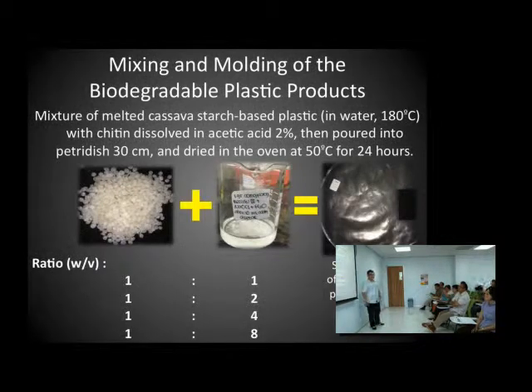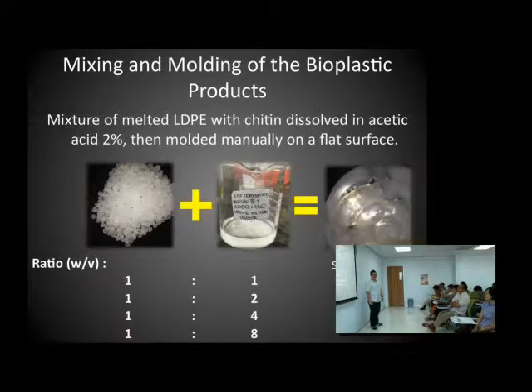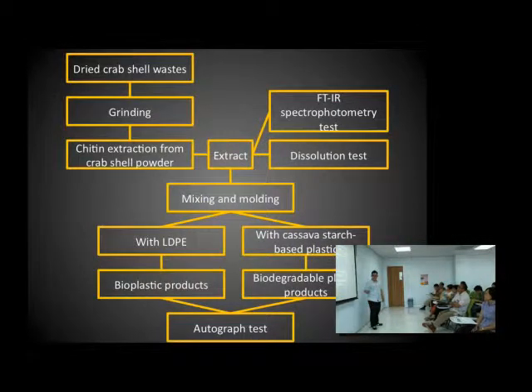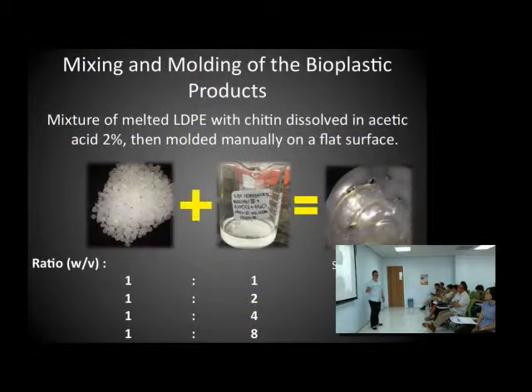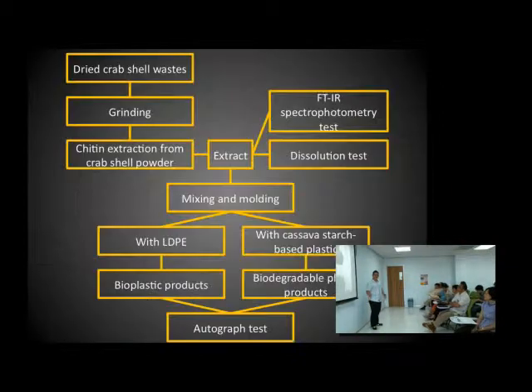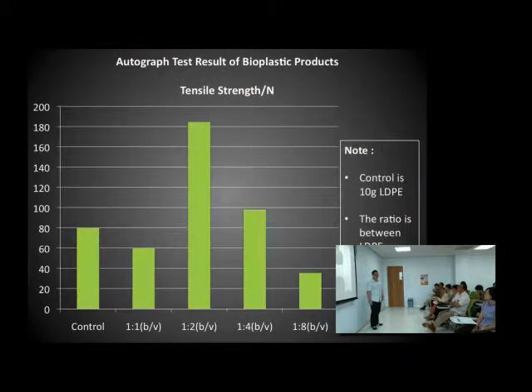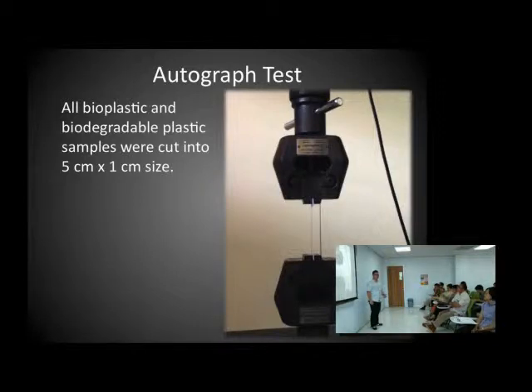After all the bioplastic and biodegradable plastic samples were obtained, I measured the tensile strength and the elasticity of the plastics using an autograph. All samples were cut into 5 times 1 centimeter size, and I also tried to do my best to make all samples have the same thickness and surface flatness.